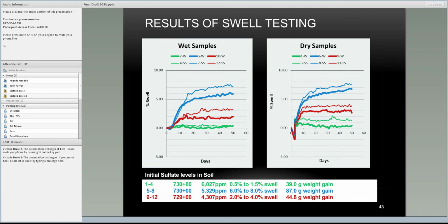And one thing that you'll notice is that station 730 plus 80, which had the highest sulfate amount, over 6,000 parts per million average sulfate, swelled the least. It only swelled 0.5 to 1.5%. However, 730 and 729 swelled quite a bit, and both of those were over 3,000 parts per million, with 730 obviously being the one that swelled the most.